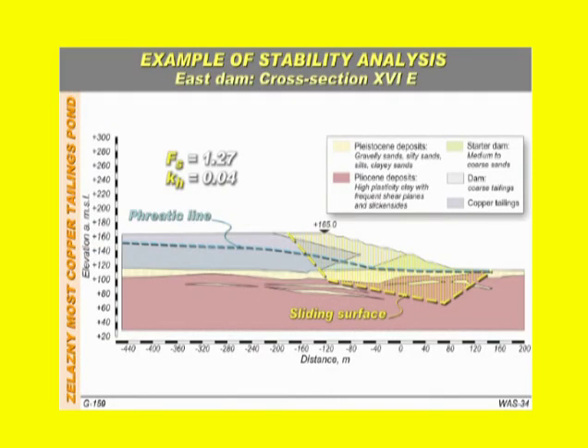The next, this is one example of a non-circular sliding surface at this critical dam cross section. We have 1.27 with the horizontal coefficient of acceleration equal to 0.04, which is too high if related to the distribution of peak ground acceleration around the perimeter. This analysis has been done before we obtained this beautiful data concerning the mining-induced seismicity.